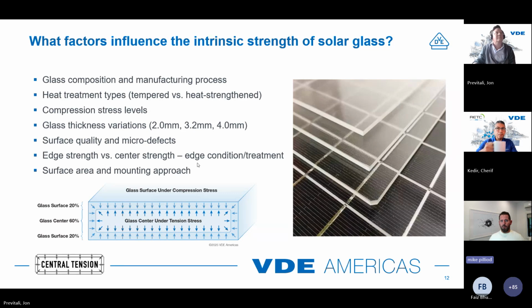With heat treatment or strengthening, if you hear the words tempered or heat strengthened glass, what that means in the case of soda lime glass is that you are inducing a secondary operation after the glass is cut and ground to shape. You go through a tempering process or heat strengthening process, the goal of which, in the bottom graphic, is to induce compression stress on the surface, and it has an internal central tension to balance the stress within the glass. So with all solar glass out there, mainly if you looked at a tempered glass, if you break it and it breaks into small fragments, what's going on there is that there's a compression stress induced in the surface of the glass.